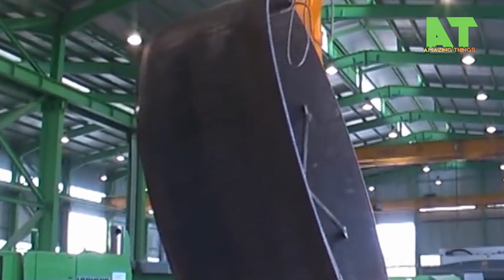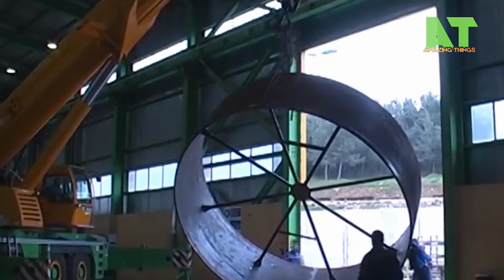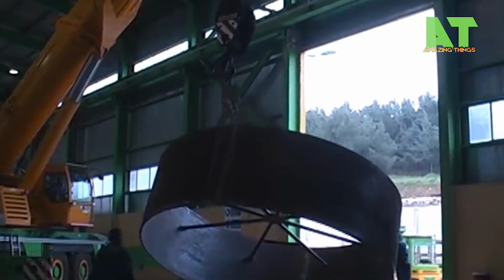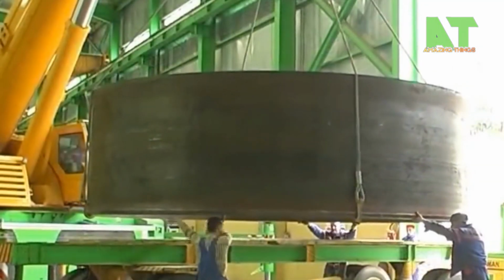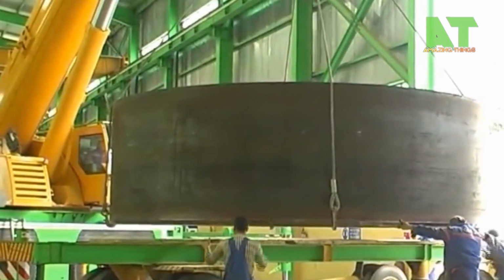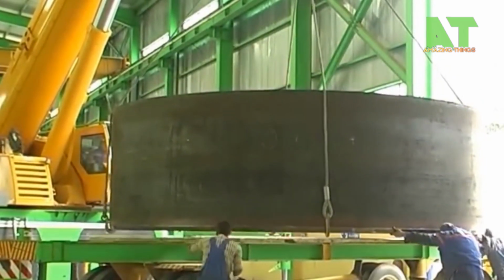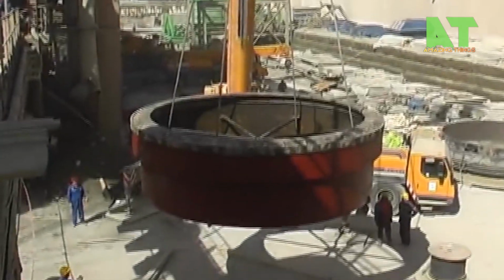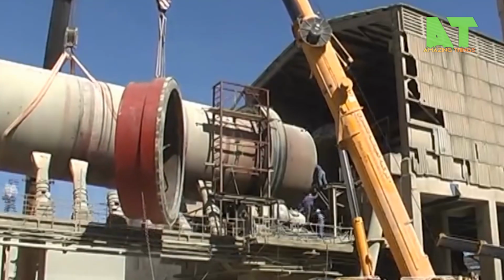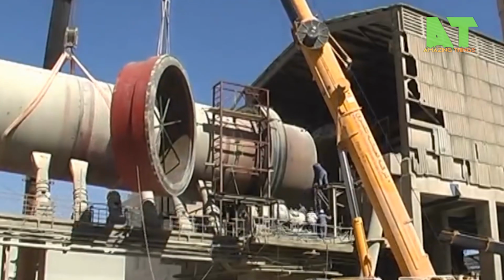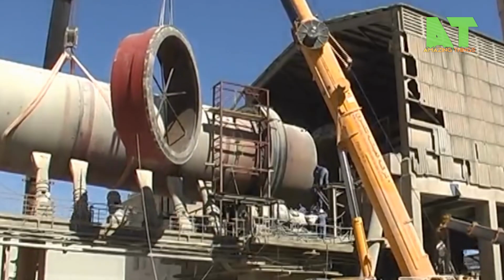Achieving a finished diameter of 6 meters with a 50 millimeter plate requires precise calculation of springback, because steel always tries to return to its flat shape after the force is released. The CNC system accounts for this automatically, applying a slightly tighter bend than the final target, so that when the force is released, the plate springs back to exactly the right diameter. The result is a rolled cylinder, perfectly round, perfectly consistent, ready to be welded into a finished component.